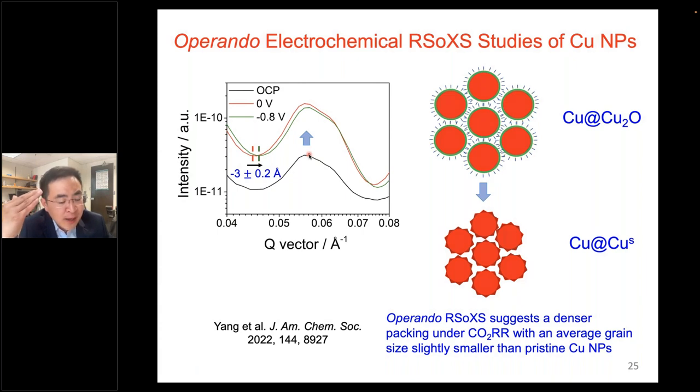That tells us that we are seeing the particle packing process, increasing particle density. And going from 0 to -0.8 volt, there is a small but reliable change because we can do very accurate fitting of the data. Indeed, from 0 to -0.8 volt, there is about a -3 angstrom change of the average domain size, which tells you the particles are merging with each other, forming nanograin